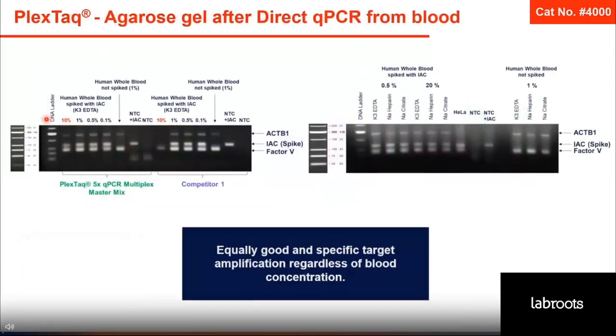This is another way of visualizing this data. We load these PCR reactions at the end on the agarose gel to look specifically for the amplifications, and we can see that for 10% of blood, PlexTaq was able to amplify all the 3 targets of interest, whereas the best performing competitor 1 managed to amplify only 1 of the 3 targets. So seeing that, we decided to challenge PlexTaq further and test how it performs with higher concentrations of blood. And for that, we used different types of blood samples and performed a comparison between performance in 0.5% of blood and 20% of blood. And as you can see, there is basically no difference in amplifications of the 3 targets depending on the concentration of blood in the sample.